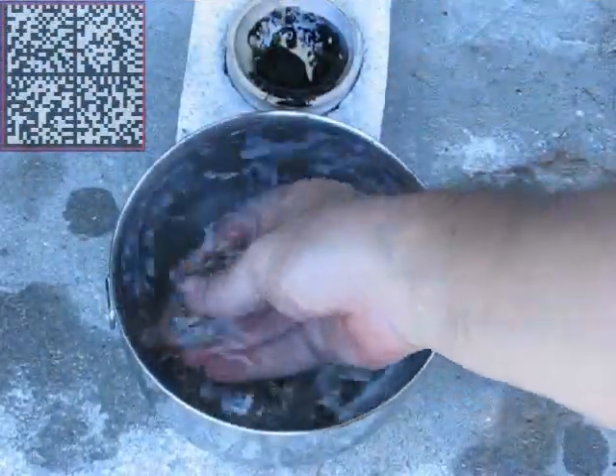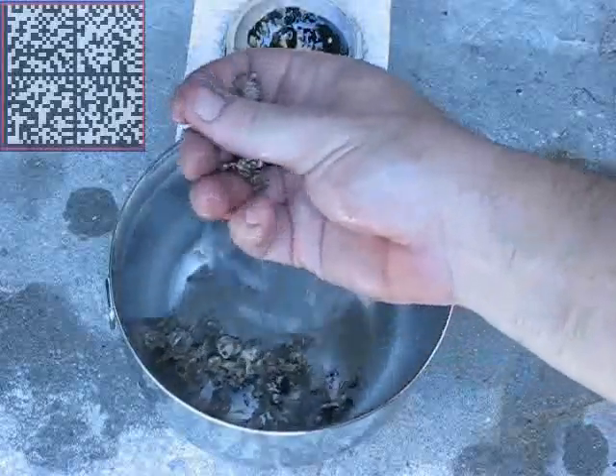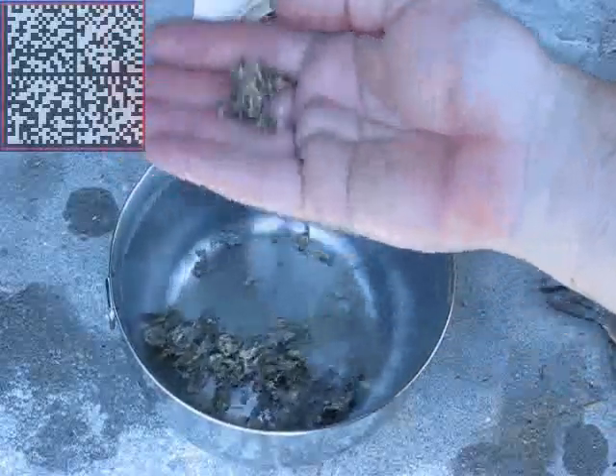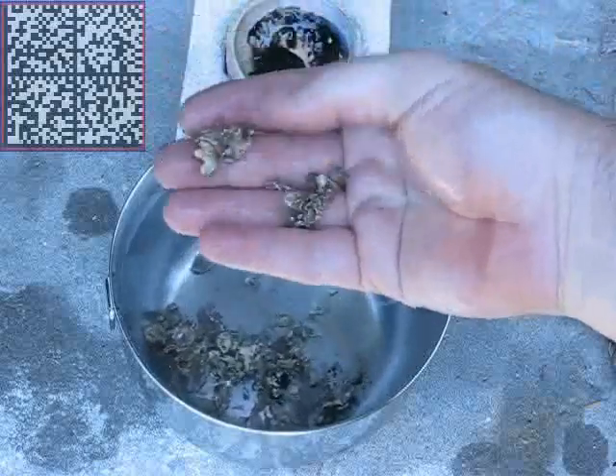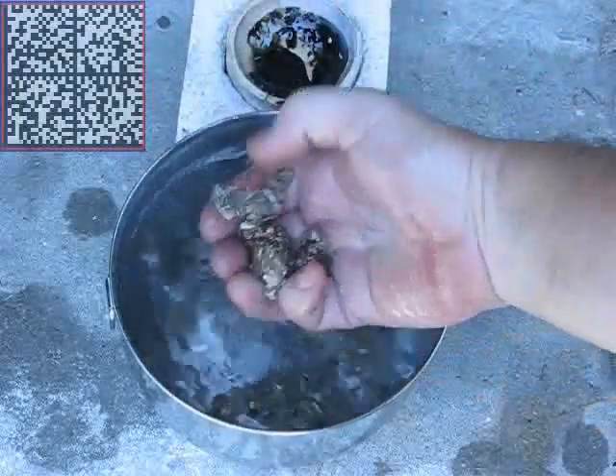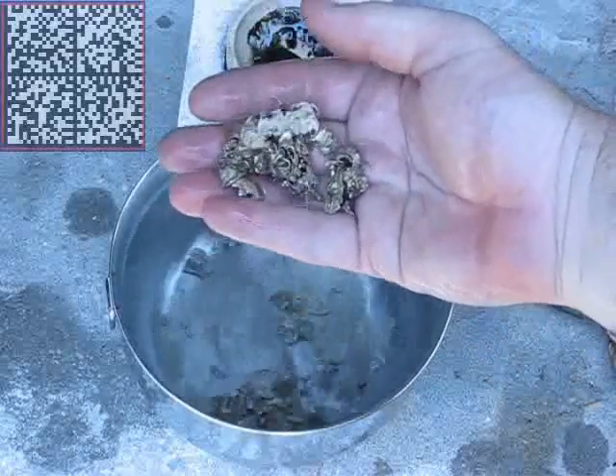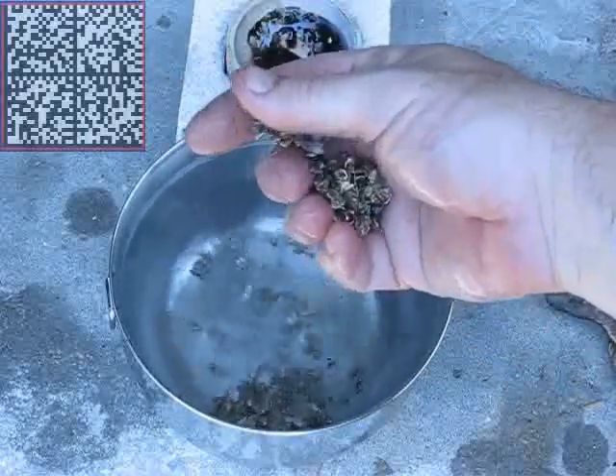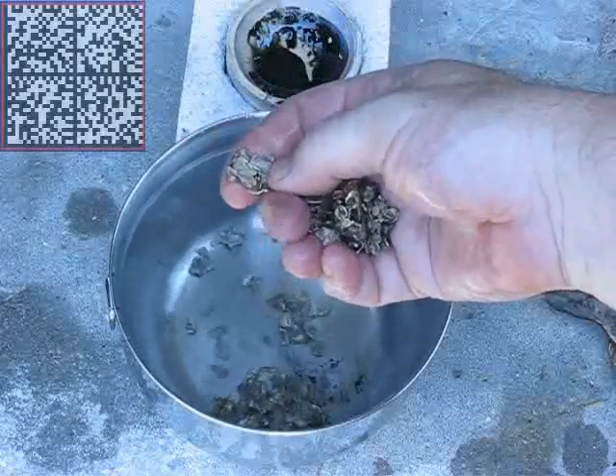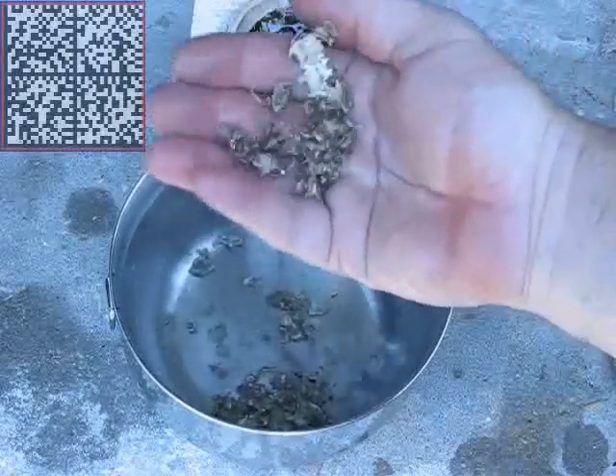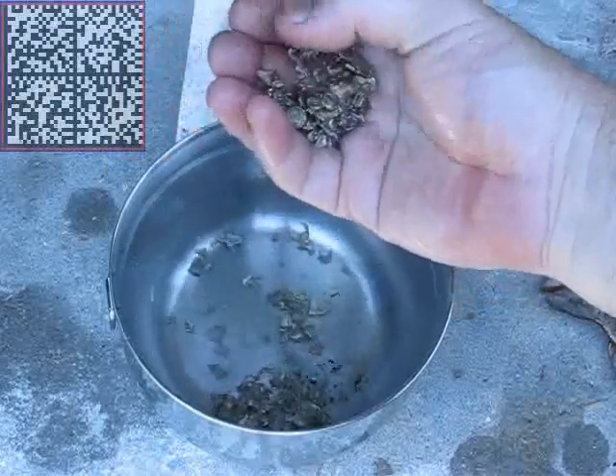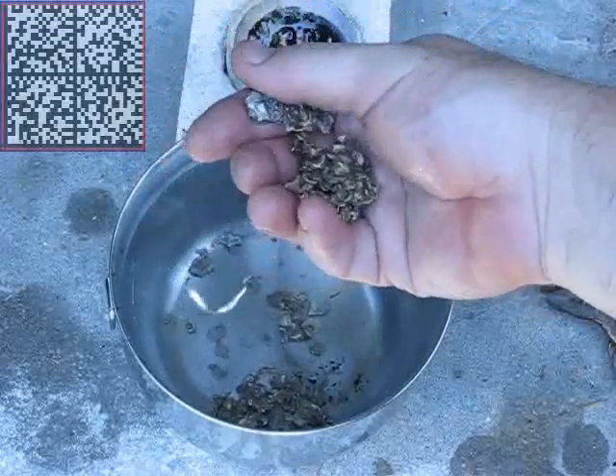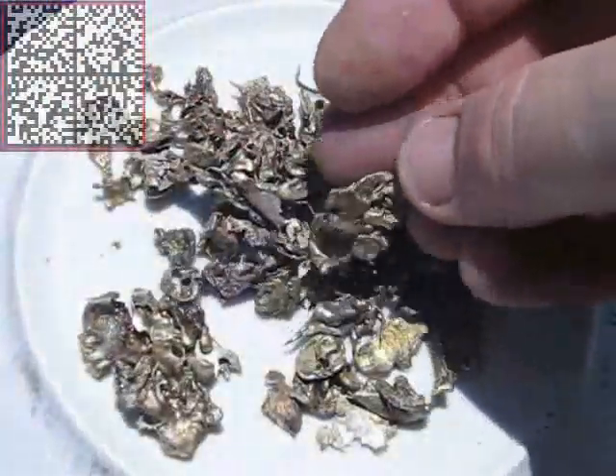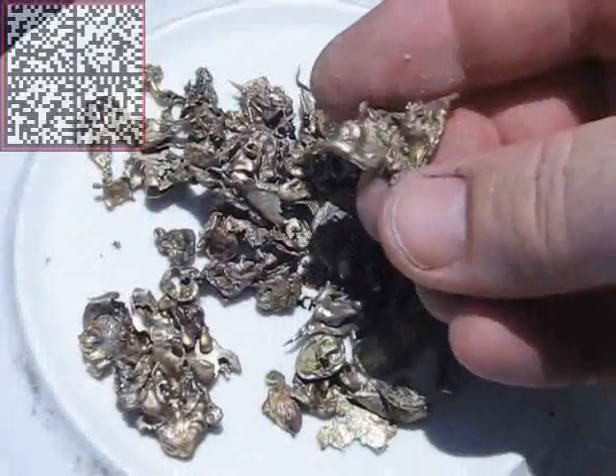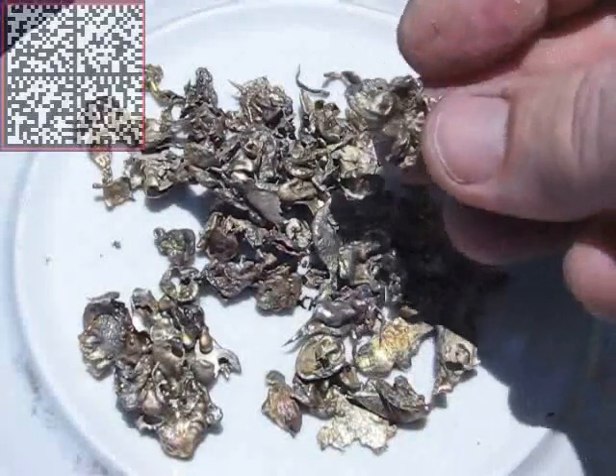Now that you've poured the alloy into the water, it's formed these flat, spread out type pieces called cornflakes. This dissolves very easily in 35% nitric acid, leaving behind a mossy type brown powder or sponge. That's your gold. Your silver will be in your solution. You want to be sure you use distilled water when you dilute your nitric acid. And that's how you inquart. The cornflakes, after they've been taken out of the water, could vary anywhere in color from silvery gold to almost yellow gold, like you see here.